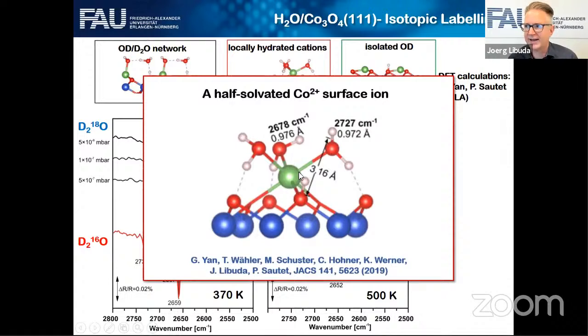This is a cobalt ion that sits on the surface, and we call it a half-solvated cobalt 2+ surface ion, because it is the cobalt surface ion that's surrounded by three oxygen ions from the oxide lattice on the one side and three water molecules on the other side. So it's the cobalt ion that is at the very interface between the water and the oxide. And you can identify the fingerprint of these species in the vibration spectrum. And in order to do so, you have to know what this structure is.